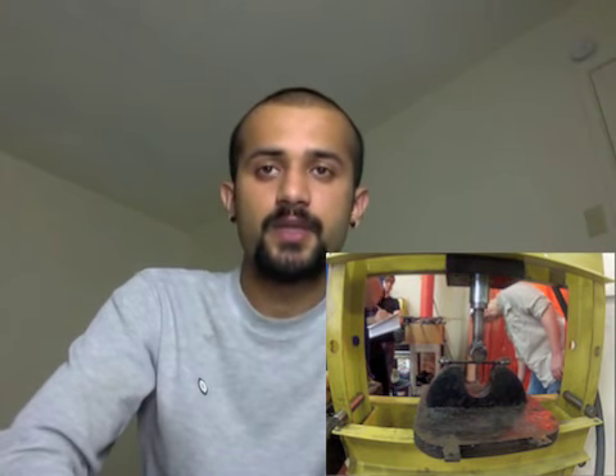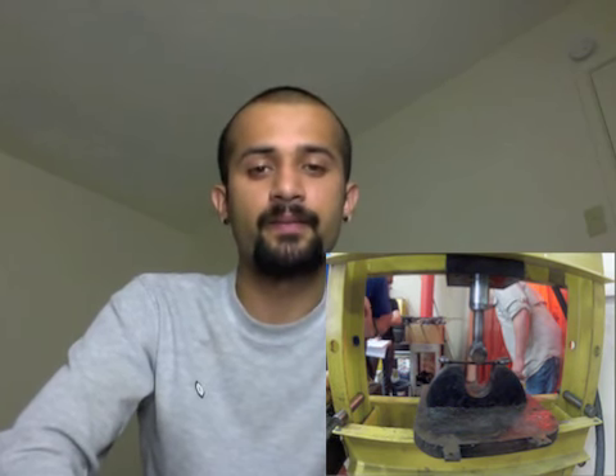The specimen provided to us was a working wrench. We took the specimen to a hardness tester and performed a Rockwell hardness test, and we found the hardness was 36, 33, and 37 on the C scale. Then we took that value and looked it up in the Machinery's Handbook, and we found out the specimen was a stainless steel. After finding that out, we took the specimen to a bending machine, and then we performed the bending procedure.